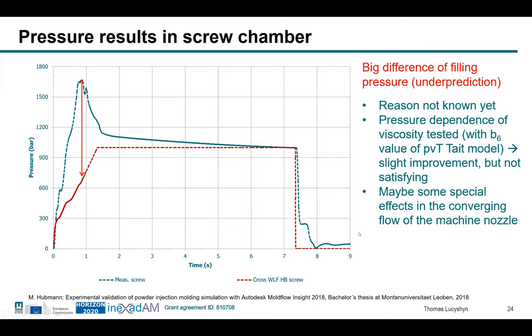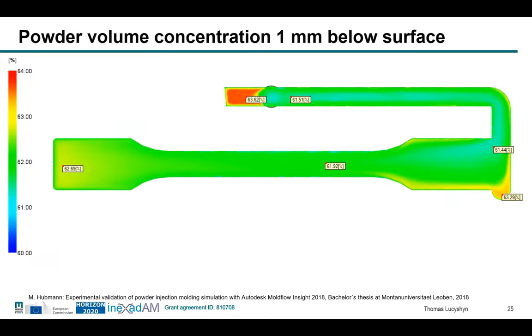So I think there is something happening inside the converging flow of the nozzle where potentially there is some blocking, where the powder is bridging and then blocking the melt flow, because basically we do not have a melt, we have powder with a concentration of 60% volume percent powder and just some polymer around the powder. So it's not really a suspension anymore. It's really powder which is enabled to flow by the surrounding polymer binder. So there is still more research work for rheologists, and we are still working on this.